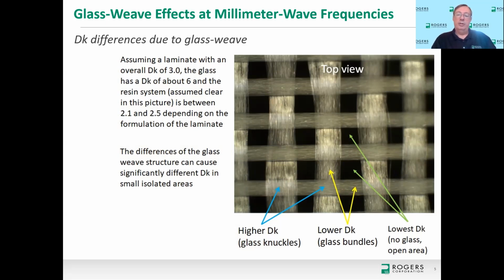So from a layer scheme from top down, you have a clear resin on top. You have one layer of glass for a glass bundle. You have another layer of glass below that as another glass bundle that's intersecting, going the opposite direction. And then below that, you have another layer of resin. So you have resin, two layers of glass, and resin for where the blue arrows are pointing. Where the yellow arrows are pointing, you have just one layer of glass because that's the glass bundle area.